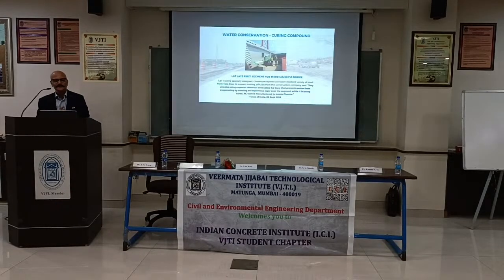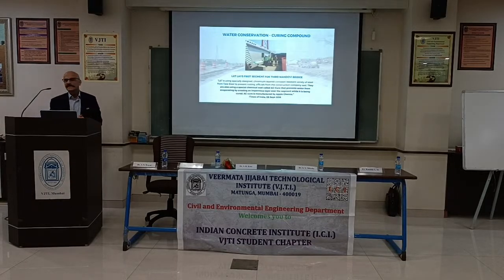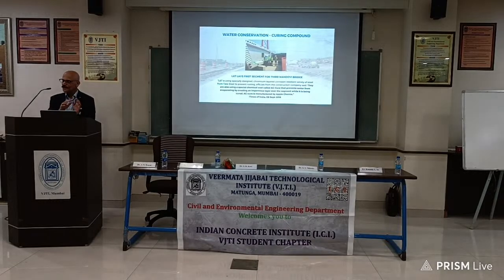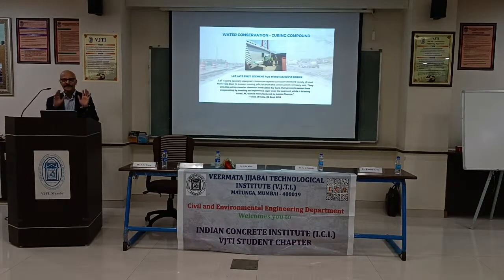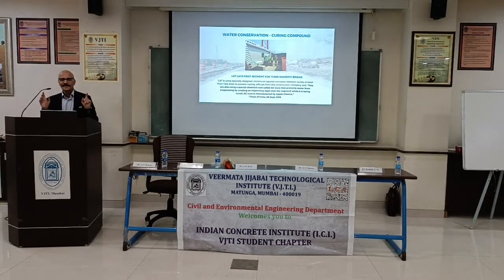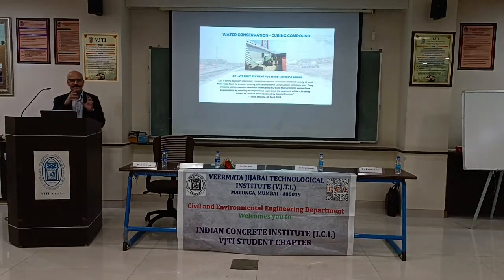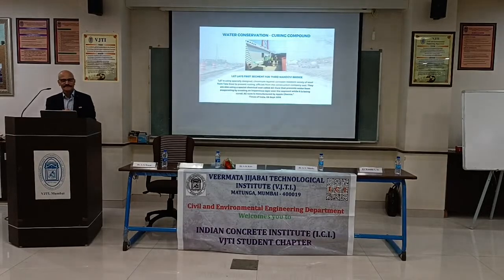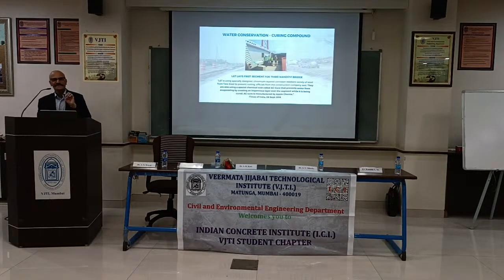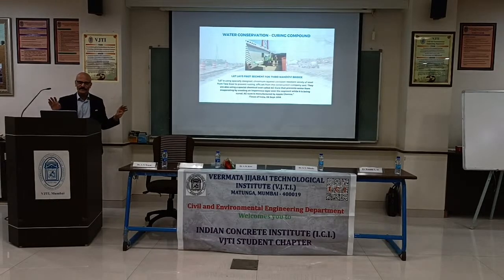There are some products which are recently being used. These are curing compounds. See, you need water for curing, but curing water doesn't add to the strength. Curing water helps to keep concrete cool, keeps the concrete protected, and if the concrete is protected, if it is cool, it will achieve the strength. So, if you have got some membrane on the fresh concrete and you wrap it up, your concrete will achieve the same strength. And in the chemistry, there is something called curing compound. It is a spray. You spray over concrete. Don't use curing water at all.